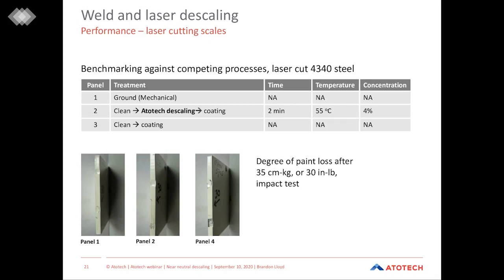You can see that panel 1 and panel 2 are very similar in performance, showing that the descaling is offering very similar results to the mechanical grinding without all the associated negative impacts that come with that. You can see that in panel 4 we see some paint loss from the impact areas, and this is exhibiting poor performance and poor coverage of the paint on the laser cut edge.